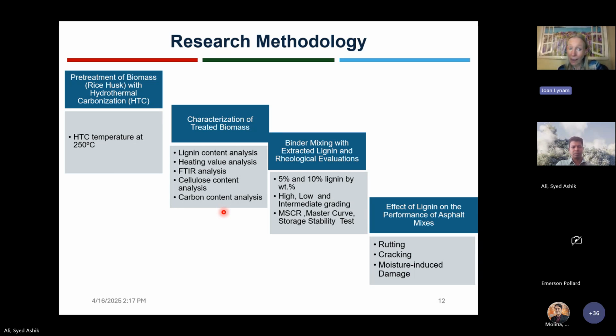We looked at the fuel value of it. We did some FTIR, or Fourier transform infrared spectroscopy on it. We checked on the cellulose content and the carbon content. Finally, we replaced either 5 or 10% of the asphalt binder with lignin.